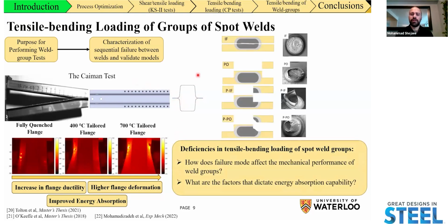But it is not really clear how the manner in which spot welds fail affects the mechanical performance of such component tests. We know that spot welds can fail in different manners. For example, we can have interfacial failure, where we have propagation of the fractures through the sheet interface, or we can have pull-out failure, where we have propagation of the failure away from the sheet interface through thickness direction, or a combination of both in partial interfacial, partial pull-out failure modes.